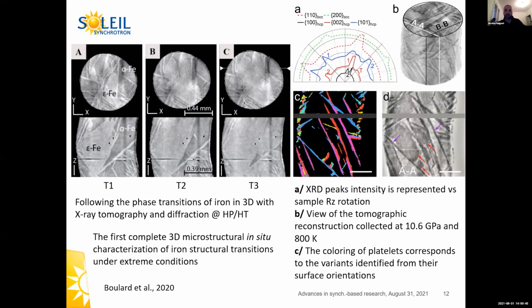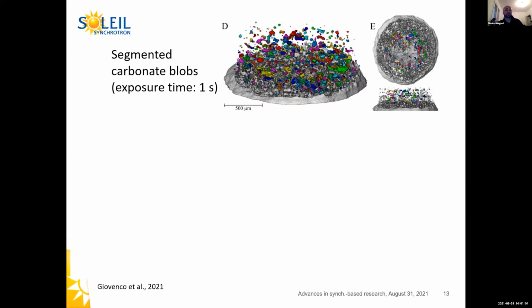But there's more. When they combine X-ray diffraction and also Fourier analysis of the 3D reconstructions, they managed to index the orientations of every platelet inside the reconstruction. The next application is a paper that has just been published last week by Giovenco and collaborators about the migration of liquid carbonates inside the silicate matrix. Here on the top, you have an example of segmented carbonate blobs from a 3D reconstruction obtained after a tomography of 1 second.